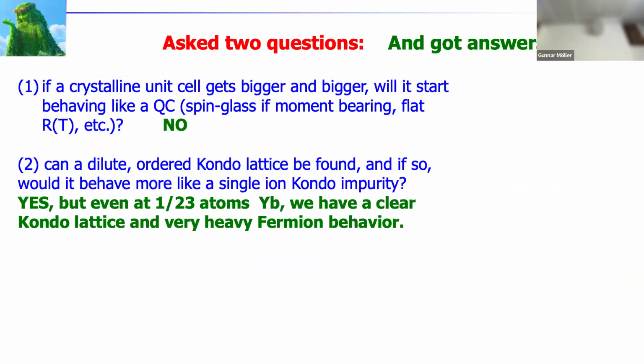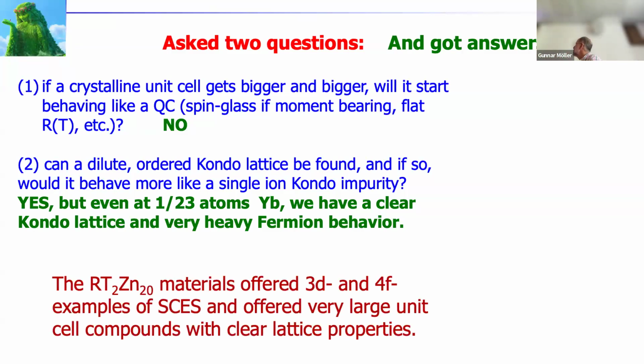Second question, can a dilute ordered Kondo lattice be found? Absolutely, 1 out of 23. Does it act like a single ion Kondo? Absolutely not. Now, again, I have a rare earth at a distance of only 6 angstroms. To get really larger, I have to start getting truly obscenely large unit cells. But at this limit, which is sort of pushing what we can do, we still have beautiful coherent behavior.